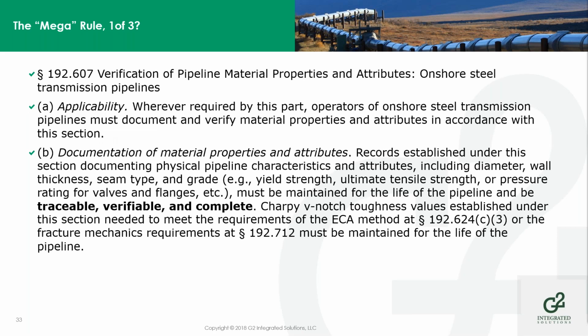607 talks about pipeline material properties and attributes. This section of the code is new. Whenever required by this part, operators must document and verify the material properties of their pipeline. And the records that have to be established under this portion of the code have to be traceable, verifiable, and complete records. Must be maintained for the life of the pipeline. So the end result of this has to be TVC records as well. The values established under this section need to meet the requirements of the engineering critical analysis method described at 624(c)(3) or the fracture mechanics requirements in 712, and they have to be maintained for the life of the pipeline as well.